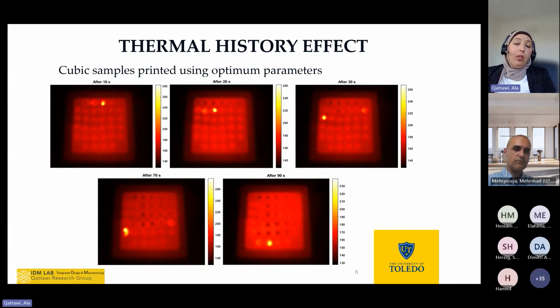The other thing, for the thermal history effect, is that with all this collective data that we have on the machine, or generally in laser powder bed fusion, scientists are trying to understand two things. The first one is whether we can predict what the defects will be in any material while we are printing, so the machine can stop, correct its path based on the images it's collecting, and improve the quality of the material we produce. The second aspect is to understand if we are able to predict the mechanical properties from the thermal imaging. If we collect a certain amount of gigabits from the machine while we're printing, and we already know the mechanical properties of the tested coupons, can we correlate that?